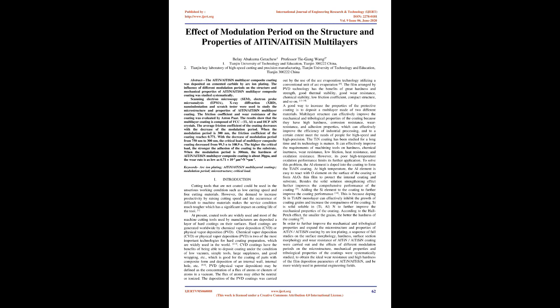A good way to increase the properties of the protective coating is to deposit a multilayer made of two different materials. Multilayer structure can effectively improve the mechanical and tribological properties of the coating because they have high hardness, corrosion resistance, wear resistance, and adhesion properties, which can effectively improve the efficiency of industrial processing, and to a certain extent meet the needs of people for high speed and high precision.